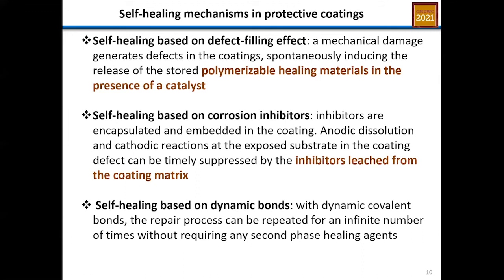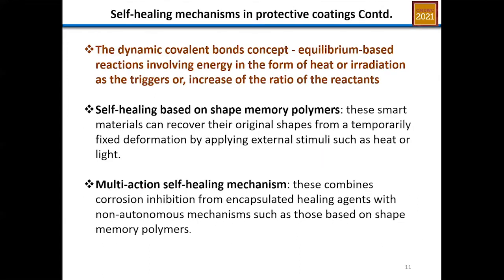It could be based on the defect healing, where you either use polymerizable healing agents in the presence of a catalyst, or where you apply corrosion inhibitors that are encapsulated and will leach out from the coating matrix into the scratch plane. In some other cases, like the intrinsic case, you have dynamic covalent bonds that, with segmental mobility, the reactive end groups can cause a repair. And in these cases, most of the time, you could have repeated healing effects. This dynamic covalent bond concept will involve some energy in the form of heat or irradiation.